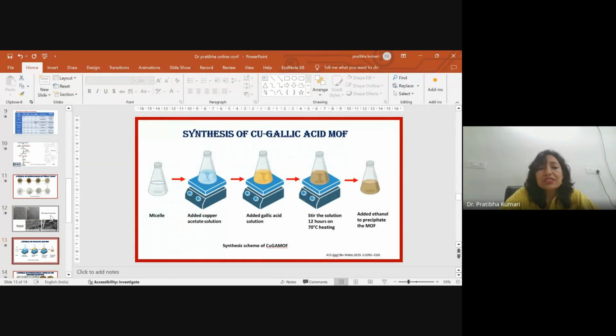And then we use this nanocellulose material to make packaging material. To have a better quality or to have an active film of this nanocellulose material, we also added copper gallic acid metal organic framework to produce anti-oxidizing property in the film to make the foodstuff safe. So we prepared the copper gallic acid MOF, metal organic framework. In the figure, you can see the scheme.